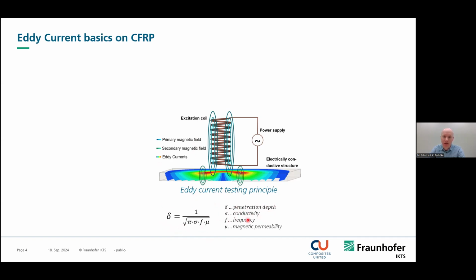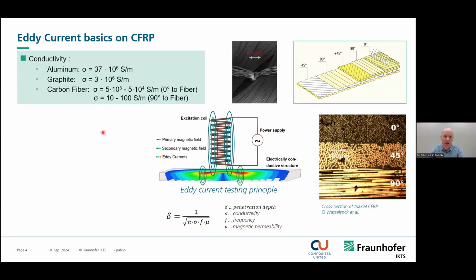We have this formula here that describes the penetration depth. That's a function of the conductivity and the frequency. The magnetic permeability of the carbon fiber material doesn't matter, so it's 1. So here you see that by increasing the frequency, we can optimize the penetration depth based on the conductivity of the carbon fiber. Here you see the typical conductivity of aluminum, 37 megasiemens per meter, and graphite has a conductivity 10 times lower.